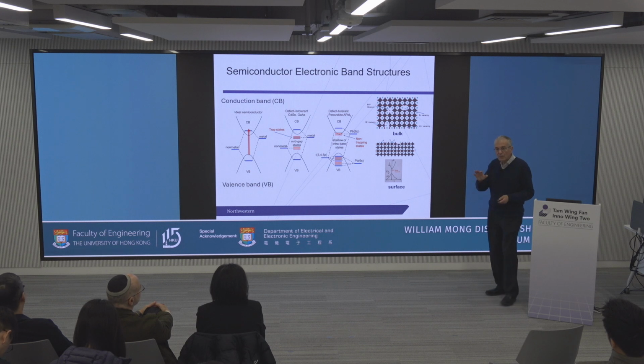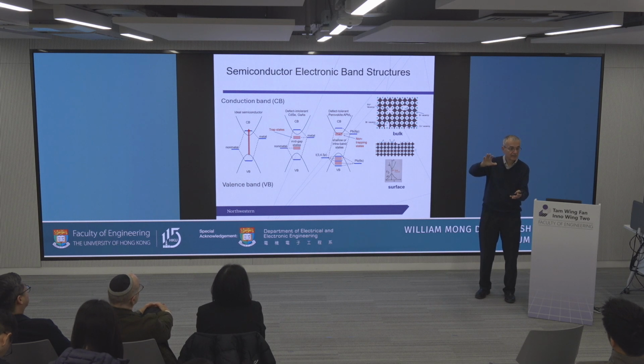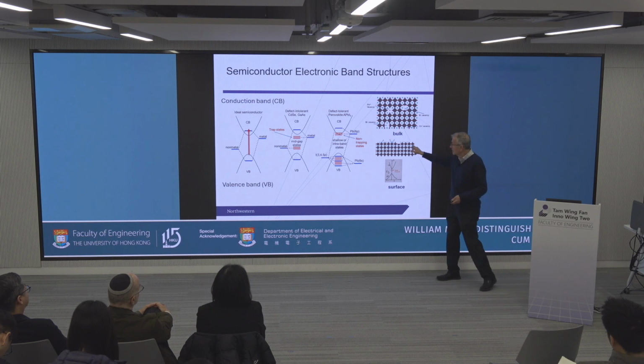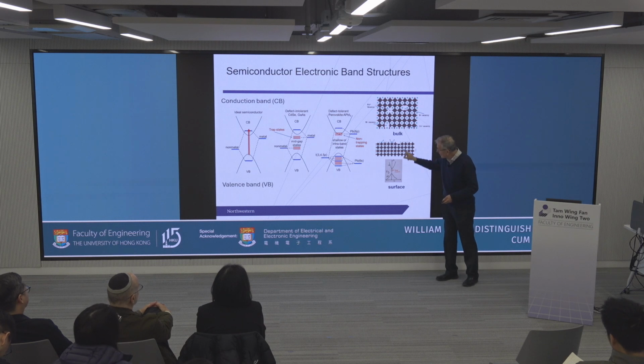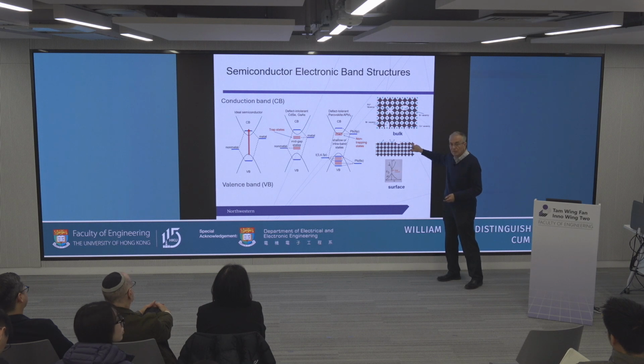And so right now we have 26%. The bulk lattice, because it's defect tolerant, can give you by itself 20% or 21%. However, the surface has defects like vacancies and other ligands here. Those can get into the gap on the surface. And so recombination happens here and you lose things.